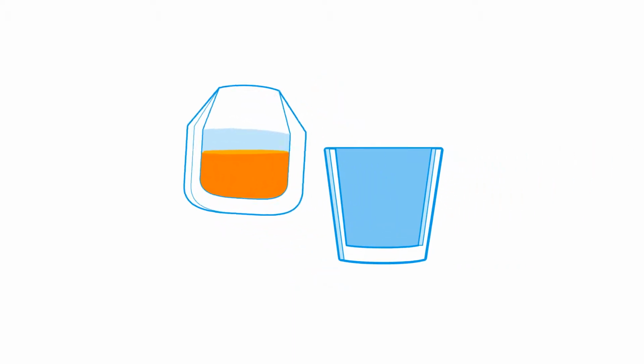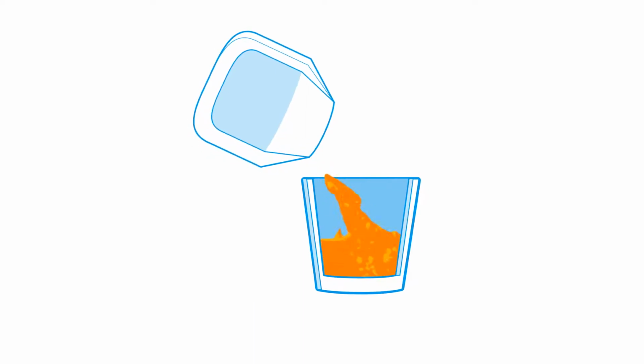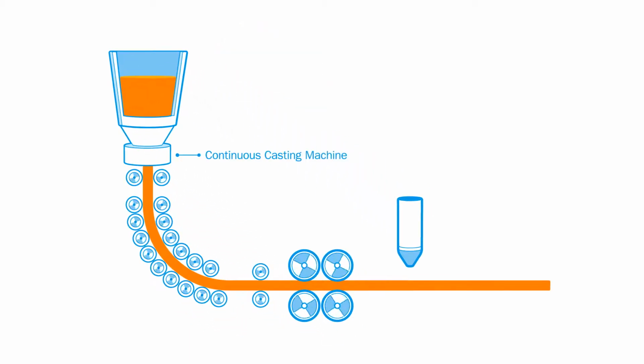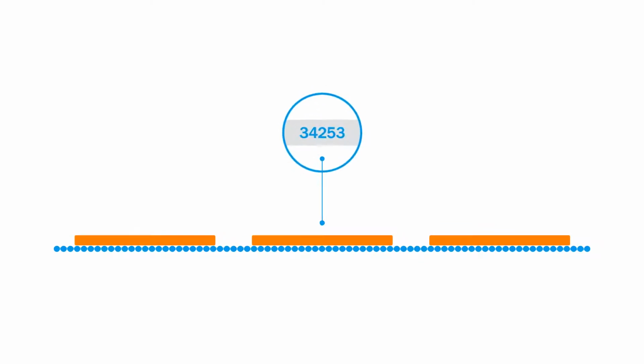The melt is poured into a ladle and transferred to the ladle treatment area, where final adjustments are made before casting. The melt is then transferred to a continuous casting machine, where the steel is cooled and cut into slabs of stainless steel approximately 14 meters long and weighing 20 to 26 tons. Each slab is marked with its own unique customer order code. These slabs are then transferred to the hot rolling mill.